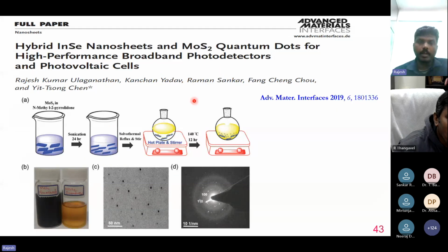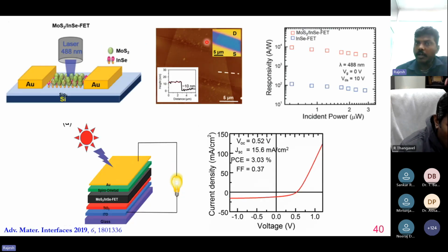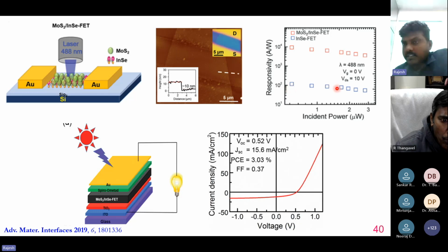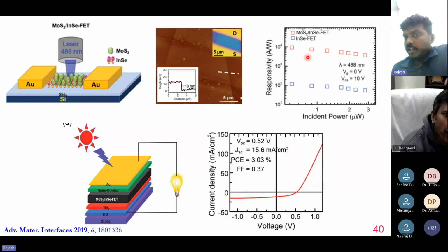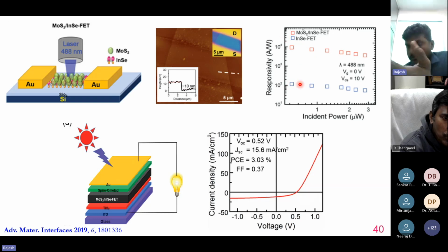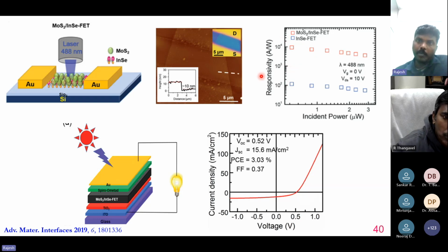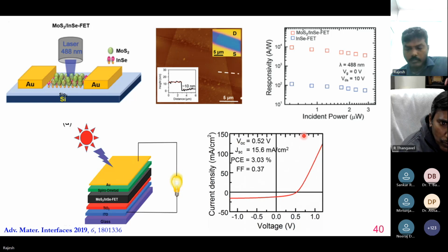Also in another work, we coated quantum dots on the surface of indium selenide. We prepared quantum dots with a simple solution process, deposited them on the surface of exfoliated indium selenide and tried to extract the device performance. We observed on a bare silicon substrate the responsivity in the order of 100. In the presence of quantum dots, it improved by two orders of magnitude higher than the bare indium selenide. We also demonstrated that the combination of MoS2 quantum dots and indium selenide can be used for solar cell kind of applications, and we are able to achieve around 3% efficiency.